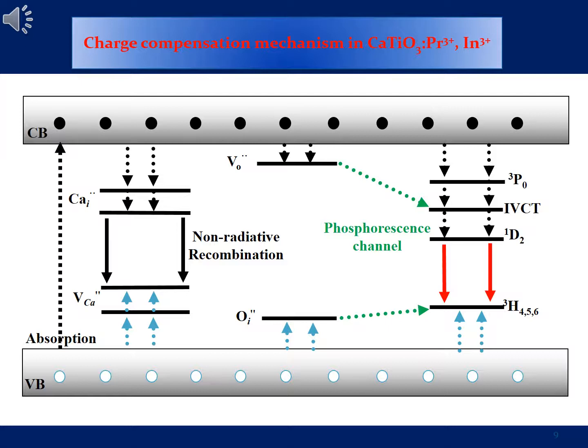material. Now, looking at this crystal structure, one needs to realize that I am looking at calcium titanate. It's calcium, a divalent ion, titanium, which is a tetravalent ion, and oxygen. Right? Now, once we have something of that nature, it means my structure is only prepared to accommodate Ca2+, Ti4+, O2-. And in any case, if I were to disturb the stoichiometry, that will result in the material generating more defects. Now, in this case, I'm substituting Pr ions in the sites of calcium 2+ ion. What do we anticipate to happen? It's divalent substituted by a trivalent ion.